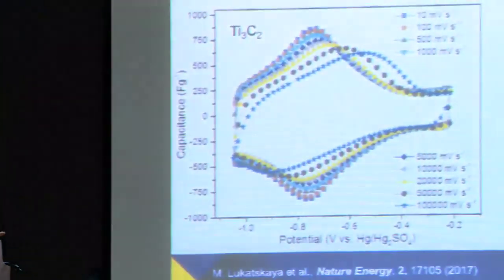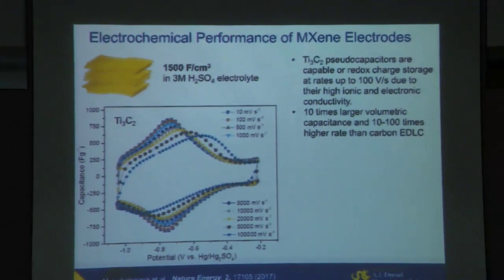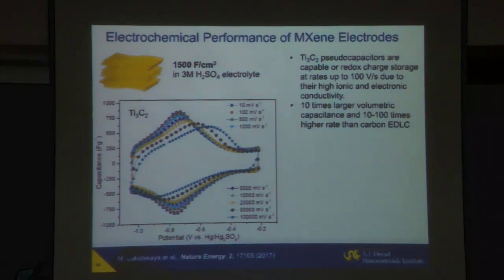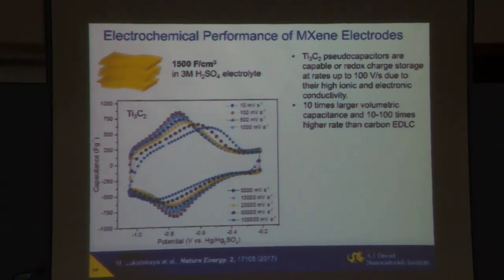Well, again, for people who are less familiar with the field, there are basically electric double layer capacitors, where quick charge storage is possible because of a double layer formed on this porous material surface. And there are materials which are called pseudocapacitors that charge quickly and charge is stored on the surface, but there is a redox process. So MXenes are really redox capacitors. And they show very, very high rate and enormous, actually like orders of magnitude, larger capacitance in sulfuric acid electrolyte. But we can get about 300 farad per cubic centimeter in organic electrolyte. We have a paper in Nature Energy earlier this year. So you can go beyond carbon.